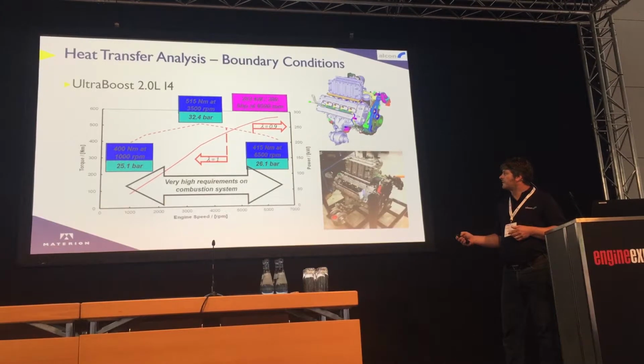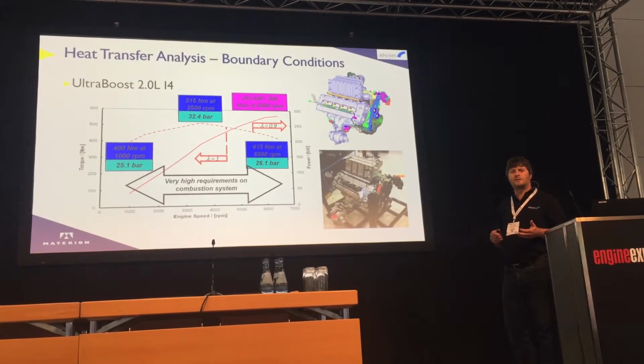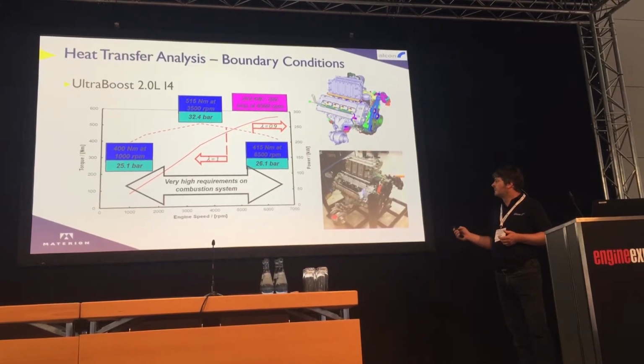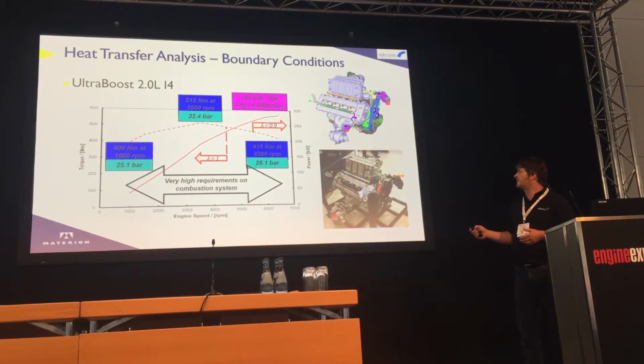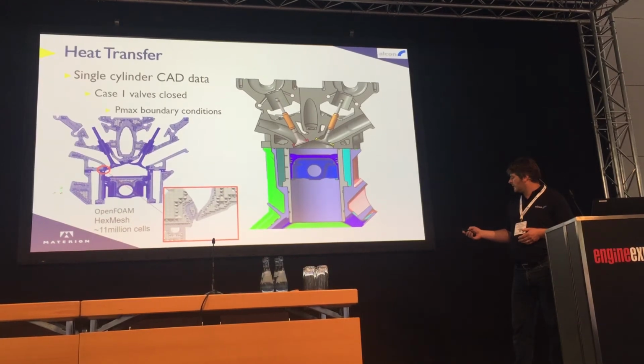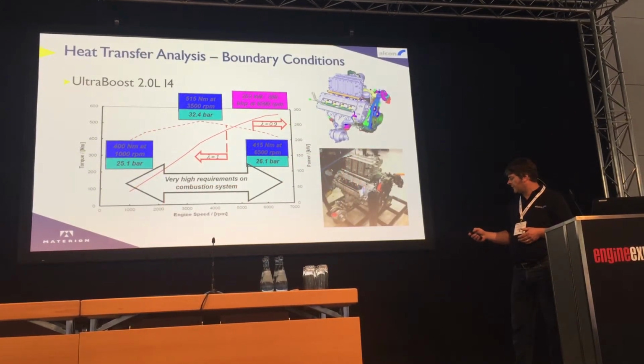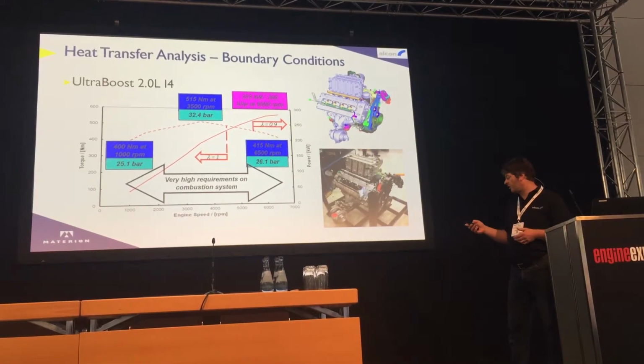In terms of the heat transfer analysis, we took the boundary conditions from an engine we've worked on over the last 5 or 6 years, which is Ultra Boost. So we used boundary conditions from this engine to feed into our analysis that we did. So it's a very high specific output engine, making 283 kilowatts. The other point to note there is the engine runs pretty much lambda 1, and the boundary condition that we used were actually lambda 1 up to full speed and full load as well, so it's running pretty hot.